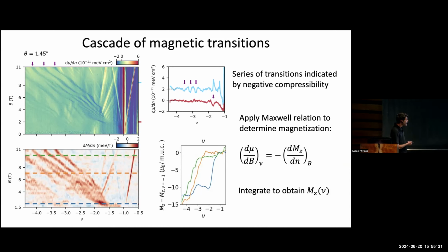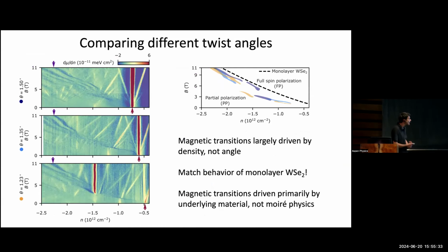And the last thing that I'll highlight is that again, we can ask the question, how do these transitions depend on the local twist angle that we're measuring? So here I'm plotting 3 different twist angles. Again, you can see in all cases, there are some blue features. These are the magnetic phase transitions. I'm plotting them not as a function of filling factor. Instead, now I'm plotting them only as a function of carrier density. And if you just mark off where all these blue features are, and plot them on the same graph, you see that they all line up very well.